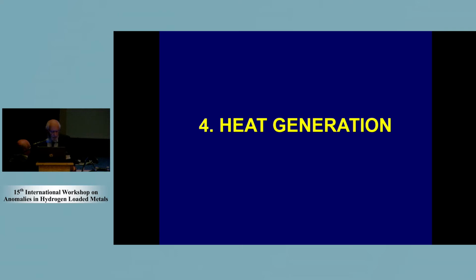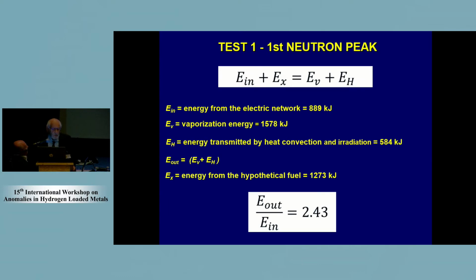Then I have the last part, which is, I think, maybe the most important. But the global results about heat generation, generally speaking, are not very good from the application point of view, because if we measure the COP over all the 10 or 20 hours, we didn't obtain a value higher than 1. But if you limit your analysis to the yellow rectangle I've shown you, I mean around the peaks, we limited our calculation around the peaks, I repeat, in that case we obtained values higher than 2. So the computation is very simple.